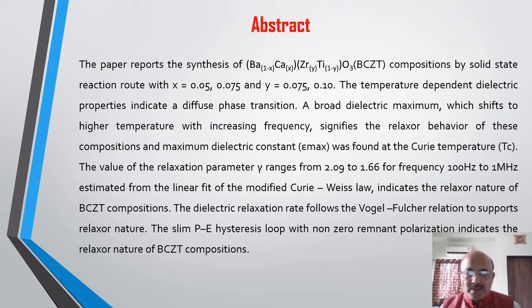The values of the relaxation parameter gamma range from 2.09 to 1.66 for frequencies 100 Hz to 1 MHz, estimated from the linear fit of the modified Curie-Weiss law, which indicates the relaxor nature of the BCZT composition. The dielectric relaxation rate follows the Vogel-Fulcher relation to support the relaxor nature. The slim PE hysteresis loop with non-zero remnant polarization indicates the relaxor nature of the BCZT composition.